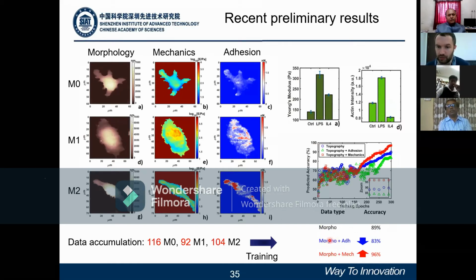If we add morphology and adhesion together, we have a decrease of accuracy. Why? Because adhesion is not well defined for these cells. Moreover, they are similar for different kinds of cells. So the signal is not helping, and even the artificial intelligence is getting more confused, so the accuracy in the automatic determination is decreasing. Oppositely, adding the mechanical feedback, the accuracy is increasing up to 96%, because the mechanics is very well defined, and then it can help for the discrimination of the cell type.